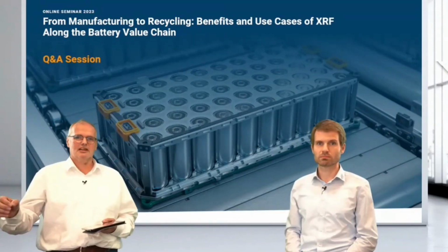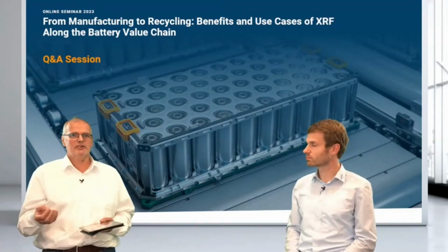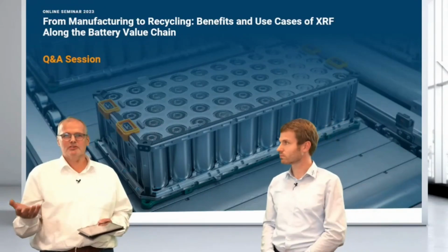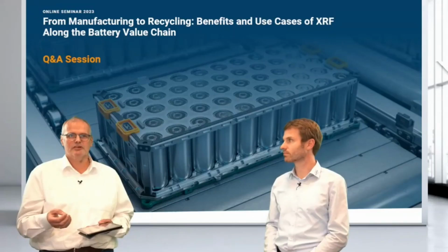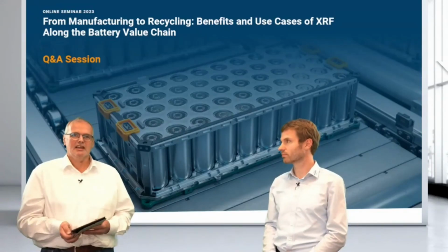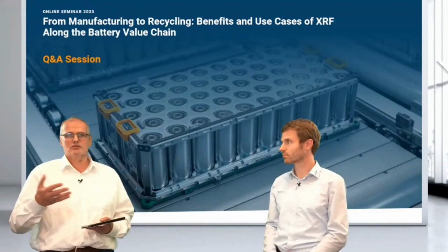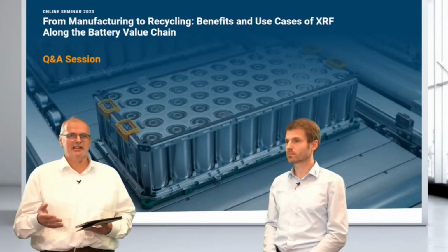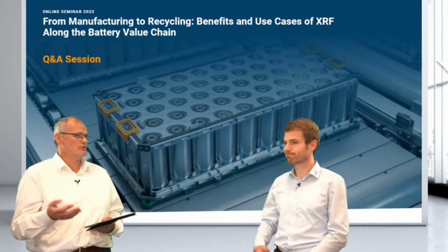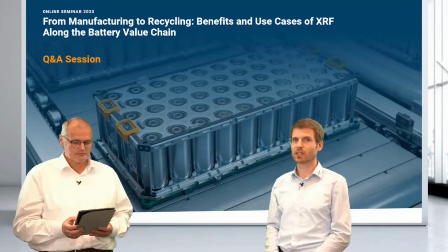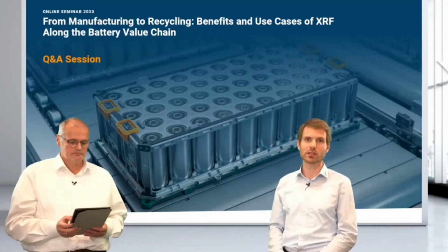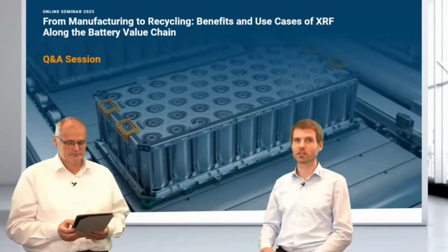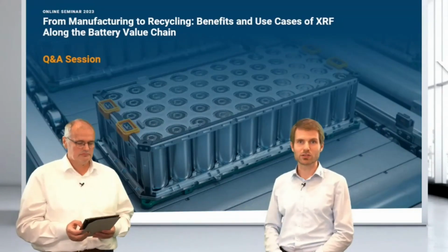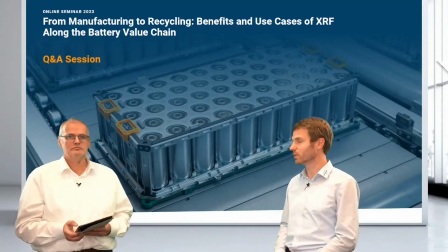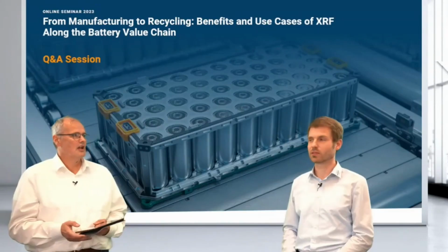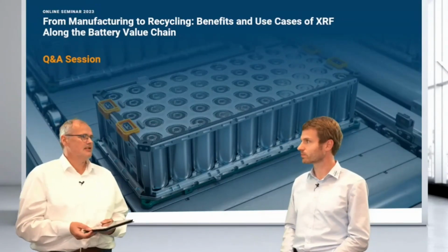It is a good micro technology, but when you look at ground material, powdered material, you will get random numbers. If you hit a carbon spot, and then you hit a cathode spot, and you need to hit an aluminum spot, so it is not very accurate, despite the fact that they promise very good analysis on the fly. Nevertheless, the material is inhomogeneous, and we are showing a pretty good mean value there. A common use case would rather be metals and alloys, which are really homogeneous, where when you hit a spot here, you hit a spot there, that should be the same composition. But in the materials we're dealing with, battery, you don't have that advantage from the sample type. How would you compare XRF and ICP in terms of impurities?